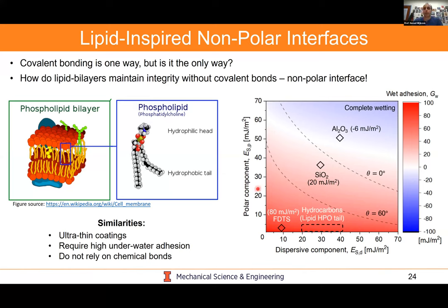What you can do is look at common materials and plot the polar component of the surface energy against the dispersive component of the surface energy. Ideally, lipid tails are down here. We have different chemistries where, if we promote the surface with something like a self-assembled monolayer before we put down our coating, we can achieve very high wet adhesions, all the way up to 100 millijoules per meter squared. In terms of the similarities, these are ultra-thin coatings, they require high underwater adhesion, and they don't rely on chemical bonds, which is a misnomer typically taught within our community to a lot of our students.